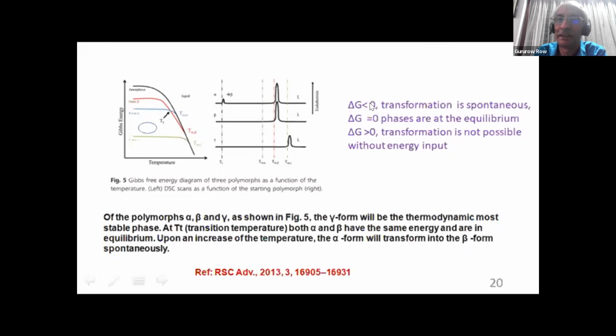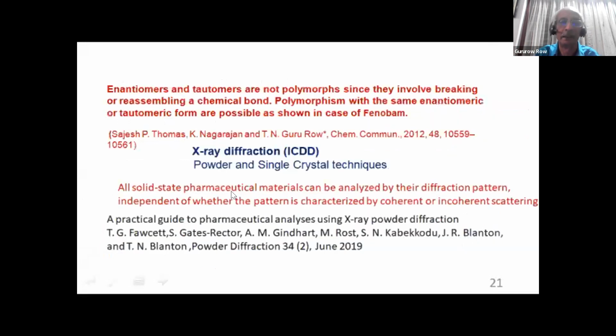If the Gibbs free energy change is less than 0, the transformation is spontaneous. And if it is equal to 0, the phases are in equilibrium. That means alpha and beta coexist at a temperature T, so you cannot now separate the two forms. They're together in this particular situation at T of T. And then alpha goes over to the beta form. However, gamma is the most stable form thermodynamically. So we can have a situation where we have all three forms, alpha, beta, and gamma, and one has to worry about how we go from one to the other.